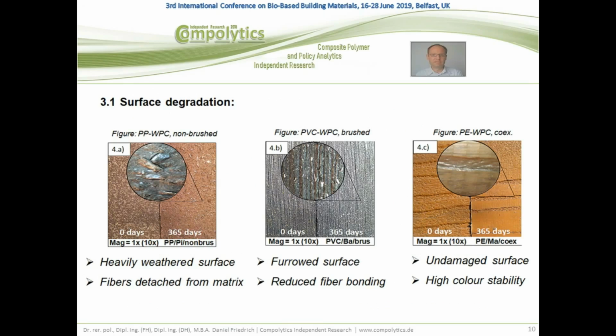After 1 year we did some microscopy investigation, and we can see that indeed the surface changed very much at the sample type where we had a non-brushed surface and we had detachment of the fibers from the surface, and the surface became very much rough. With the second type, with the PVC matrix, we observed furrows and slight crackings in the surface and also fiber detachments, and the lowest change in surface quality we received with the sample with the co-extruded top layer, which protected very much the surface exposed to the natural weathering. So here we had the lowest change at all.